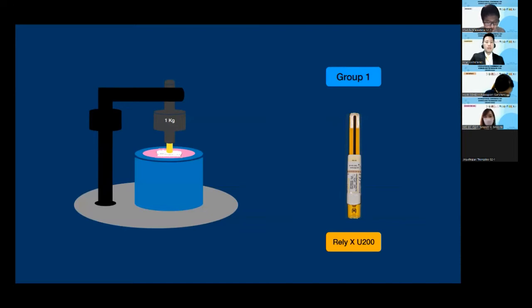Then for group 1, the Rely X U200 was applied on the dentin with a micro brush, and the resin composite cylinder was placed and pressed by 1 kilogram of force, and the excess cement was removed with a micro brush. Then photo-activation was performed for 40 seconds from the side and another 20 seconds on the top of the composite cylinder after unloading the loading device. For group 2, the procedures were quite similar to group 1, but required additional pre-treatment steps.